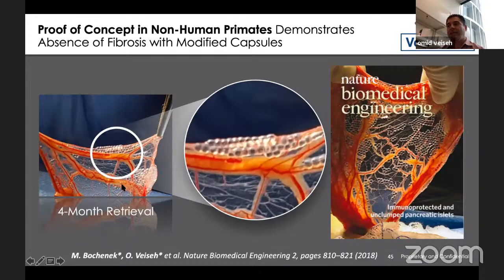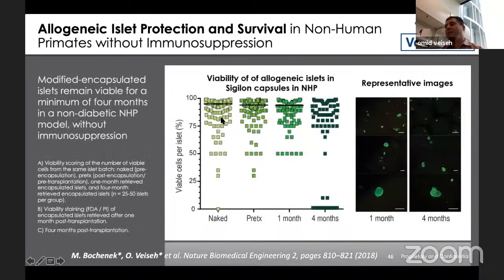It's a sac that actually exists in the IP space. It's covering the liver, and it's accessible in that you can actually put capsules inside of this sac. And we found that we even get better outcomes when we take our modified alginates with the cells and put them into this area. And then, this is 4 months later without immunosuppression, we take these out, and these capsules actually all look translucent, no fibrosis. And when we assess the viability of the cells on the inside, we see that more than 80% of the cells are viable and able to remain functional with no immunosuppression in non-human primates.